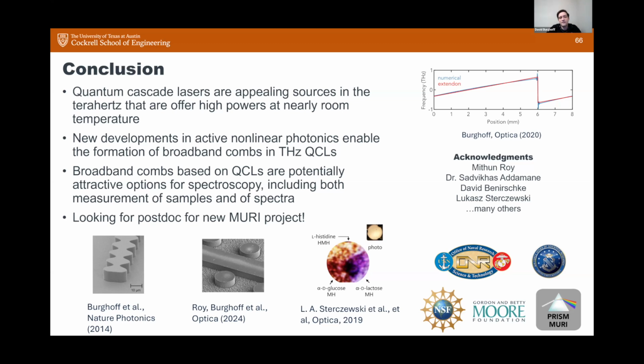Generally speaking, it depends on how many devices you want to make, right? You can make a lot of devices with a 4-inch wafer, thousands in theory, but it takes some effort to replicate that wafer. And when you replicate it, it doesn't quite replicate perfectly. Many people in this area have had the experience where they see a design in the literature and try to grow it three or four times. Eventually they get something that is more or less close enough, and they decide, okay, we'll use that. So you can get something approximating it, often with multiple attempts.